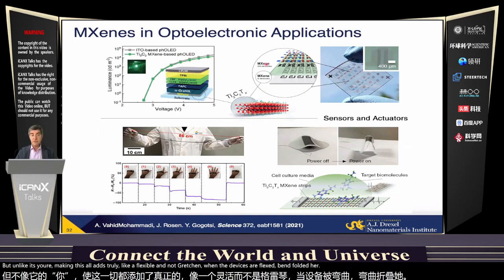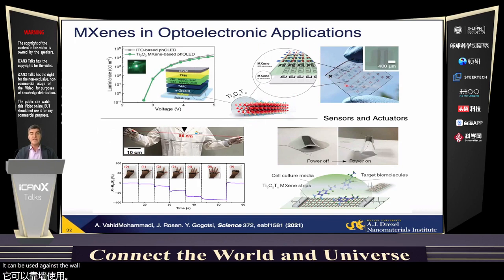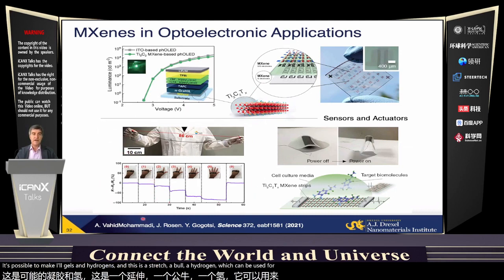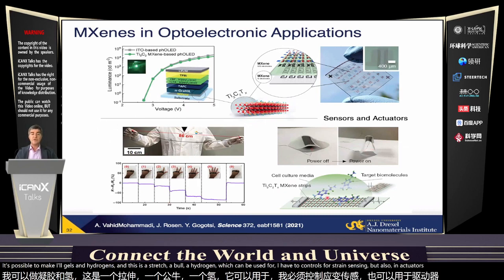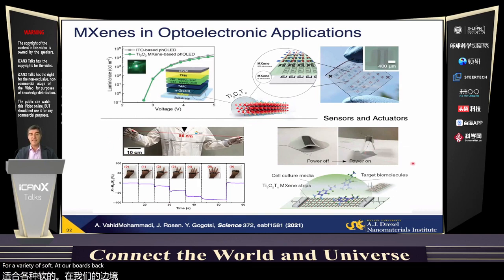It can be used again instead of gold in current collectors for printing here. It's possible to make aerogels and hydrogels, and this is a stretchable hydrogel which can be used for haptic controls, for strain sensing, but also in actuators, also electrochemical and optical actuators for a variety of soft robotic and sensing